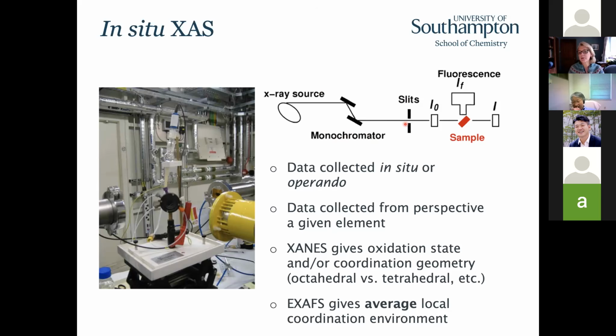We clean up the beam with the slits. We have to measure the intensity of the X-rays before we go into the sample. And then we can either measure our data in transmission, so we measure the absorbance, or we can measure the fluorescence. One of the great things about using X-rays as our spectroscopic probe is that they're very penetrating, and that allows us to collect the data either in situ or under operando conditions.